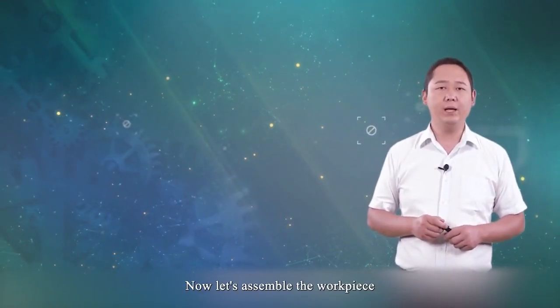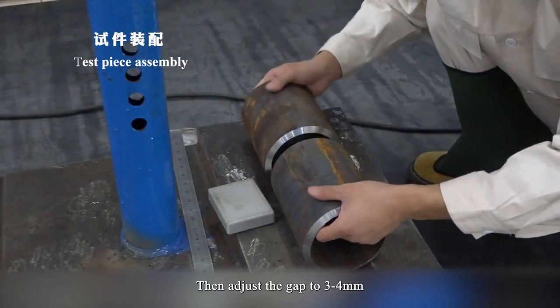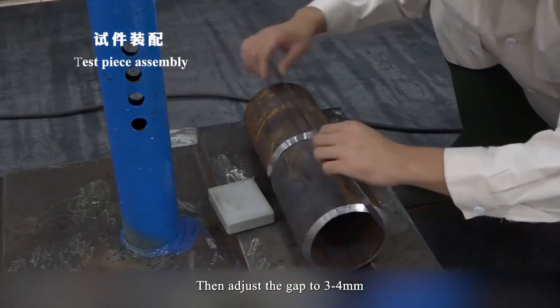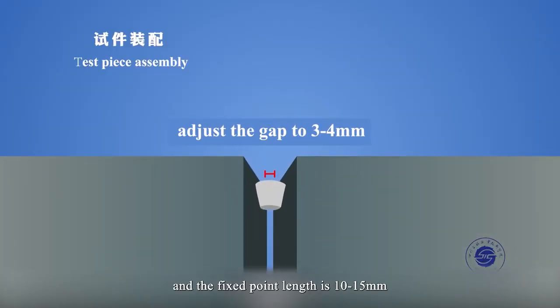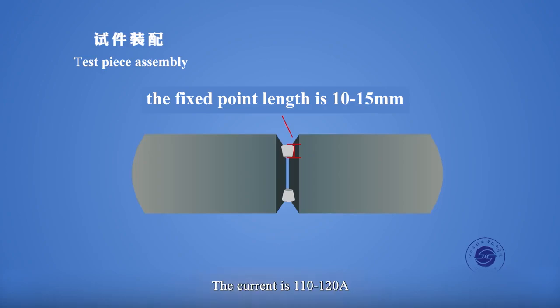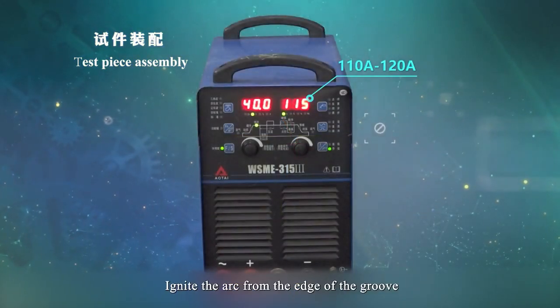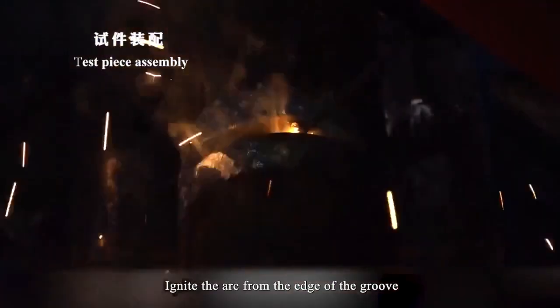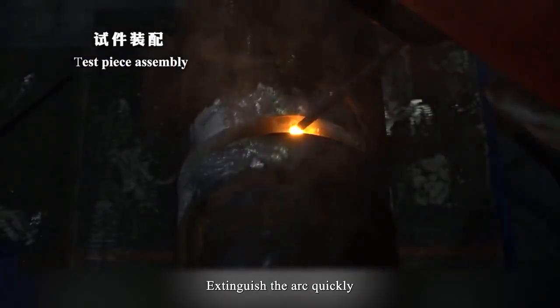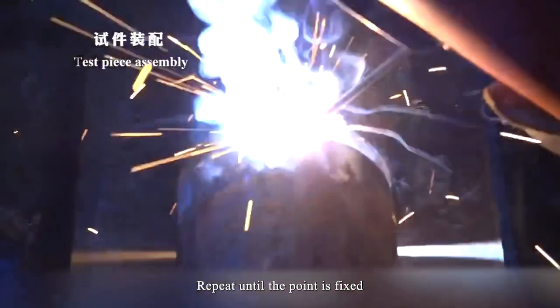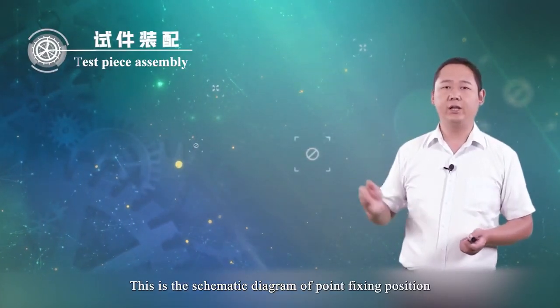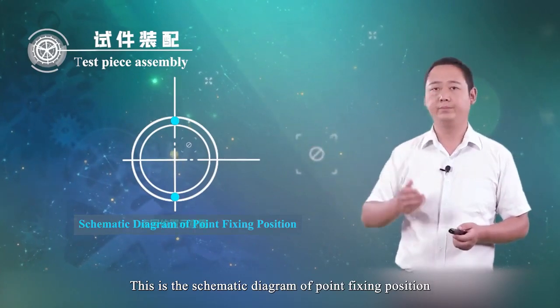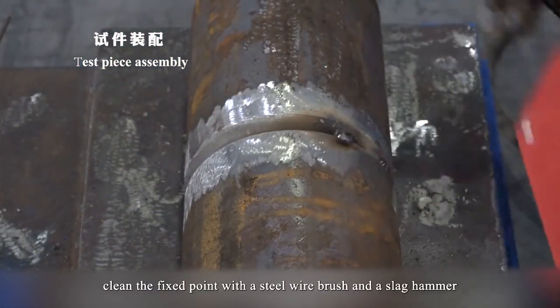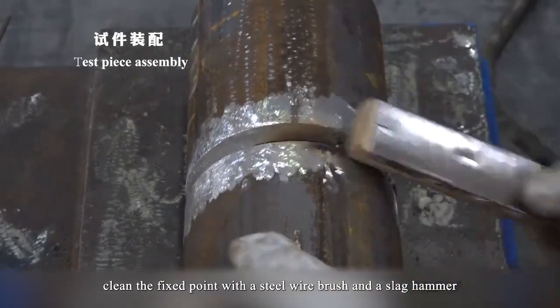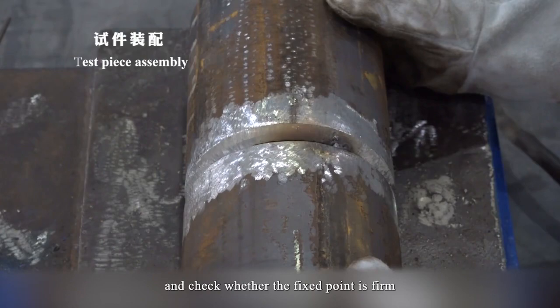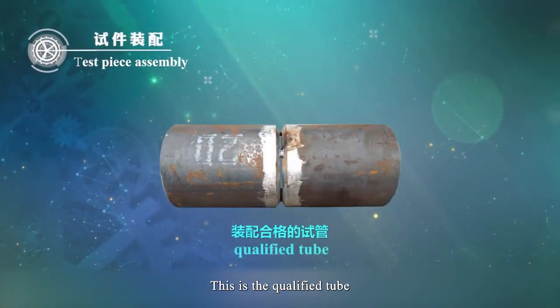Now let's assemble the workpiece. First, place the tube on the angle. Then adjust the gap to 3 to 4 mm, and the tack weld length is 10 to 15 mm. The current is 110 to 128 amps. Ignite the arc from the edge of the groove, then pull it to the middle of the groove. Extinguish the arc quickly. Repeat until the point is fixed. Two points are fixed. This is a schematic diagram of the tack weld positions. Finally, clean the tack welds with a steel wire brush and a slag hammer and check whether the tack welds are firm. This is a qualified tube.